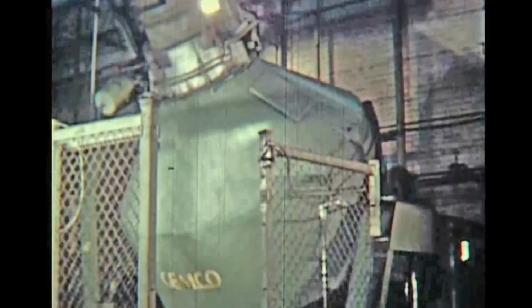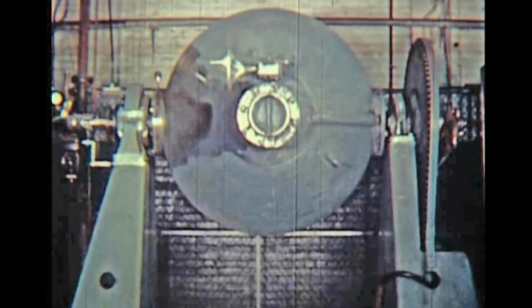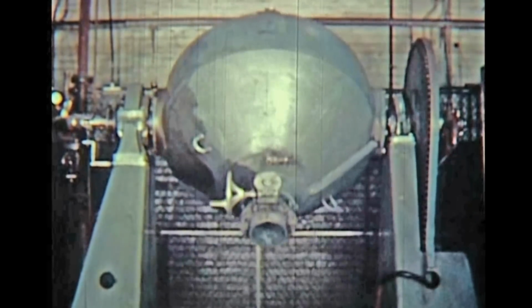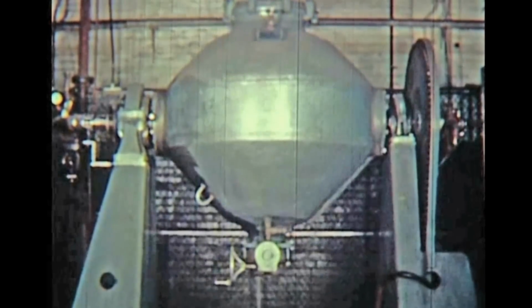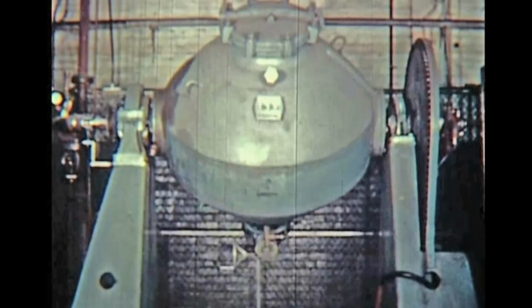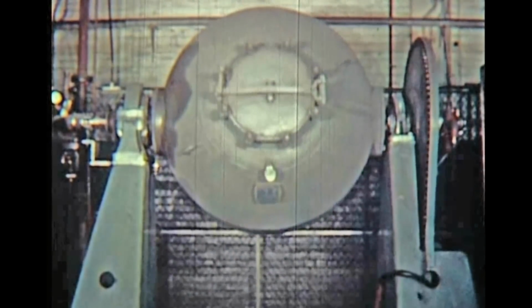To homogenize the batch, the oxide is placed in the Gemco blender. Only blue oxide is used for 218 powder and must meet specific standards of purity and particle size. To obtain the non-sag characteristic for 218 wire, the oxide must be doped. For many years, this was done in large bowls by hand. Today, we have a blender in which the oxide can be thoroughly mixed with potassium, silicon, and aluminum doping agents, and then dried in a vacuum by heat from a steam jacket.